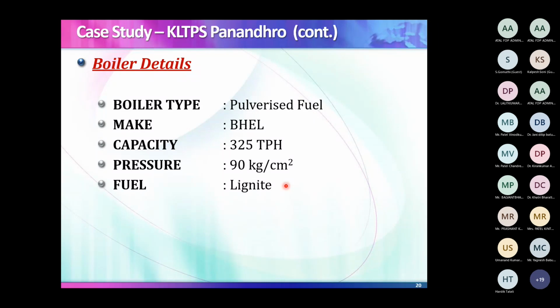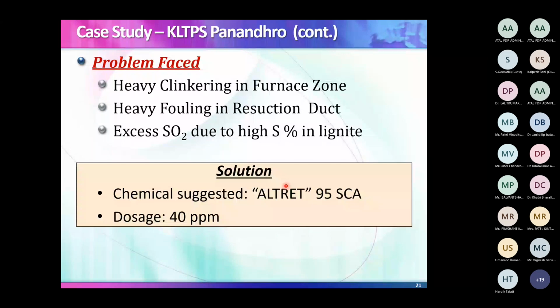Then I designed an additive and gave it the name SCA. That is my name, it's a SCA. That was the name given to that particular additive. The problems they were facing were heavy clinkering in the furnace, heavy fouling in the reheater section, and very high SO2 emissions because of high sulfur in lignite. So what I suggested was we developed another additive, 95 SCA. You know, my name appears here indirectly, and the dosage was 40 ppm, that means 40 gram per ton.